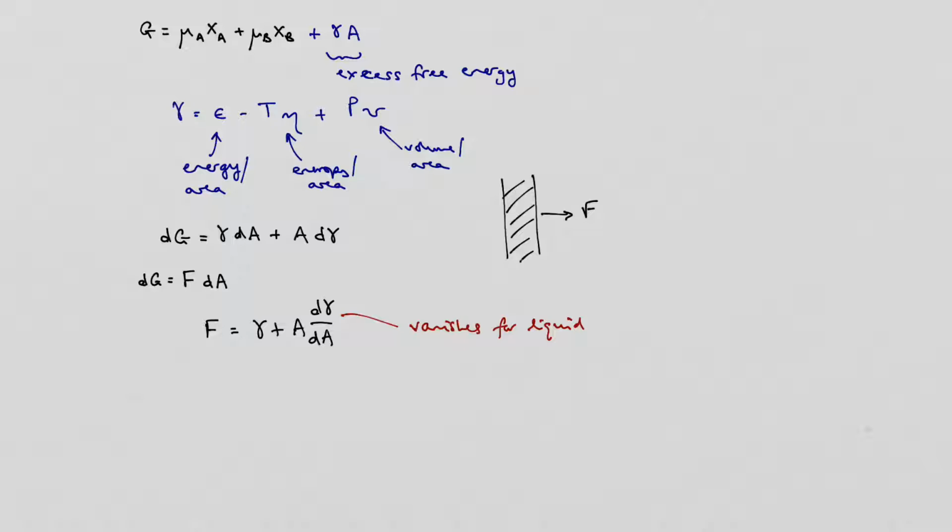And therefore you get the result that you may be familiar with, that in a liquid, surface tension, the energy per unit area, is also equal to the line tension, the force to maintain the area. Okay? But that is not true when it comes to solids. It's just to say that if you've seen this before, you've probably seen it in the context of surface tension, and there's a slightly special case there. In solids we have an additional term as well. Okay, this one here.